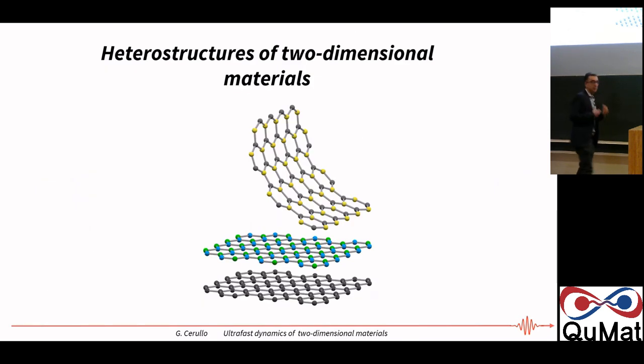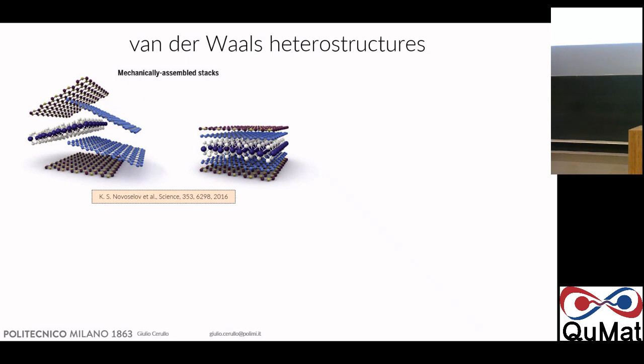Now, in the last 10 minutes, I want to move to heterostructures. Now, the power of these materials is that you can really stack them, each one on top of the other, doing mechanically assembled stacks, where you can make sandwiches of these materials that are held together by interlayer van der Waals forces. And this is very different. In a normal semiconductor, if you want to make a heterostructure, you need to be careful that the different materials have similar lattice constants. So it's not easy to put two semiconductors on top of each other. But here, since you have this van der Waals interaction, you are really free to put, for example, one material on top of graphene and then make sandwiches of different materials.